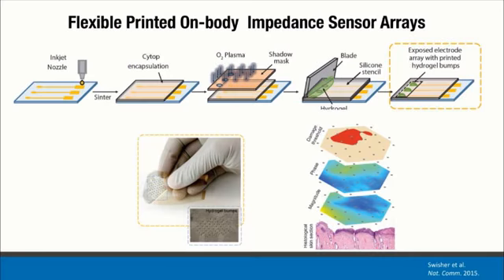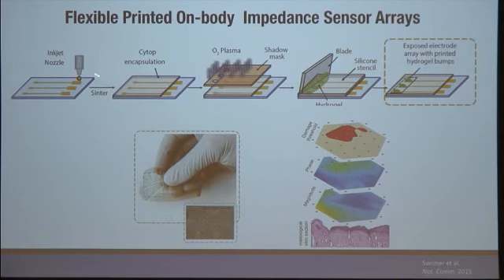This is a further example of more complex process integration of some of the kinds of things you can do with this sort of technology, where we've used that printer, the inkjet printer you saw in the previous stage to print maybe electrode traces. There's various encapsulation, oxygen plasma step, which is going to then pattern an additional blade coating deposition using wetting and de-wetting. The oxygen plasma through a mask locally produces very high wetting areas, and then the counter area is very de-wetting, and then you can literally scrape another ink across that of another material, and it will essentially completely de-wet off